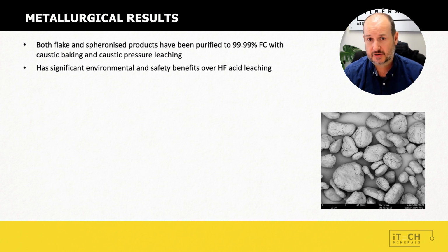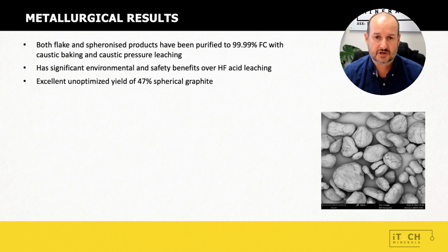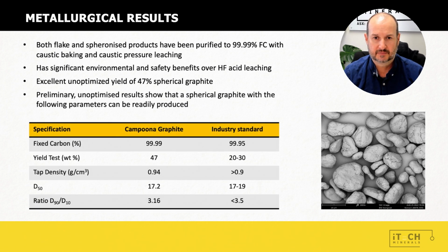Both the flake and the spheronized products have been purified to 99.99% fixed carbon using both caustic baking and caustic pressure leaching. We were also able to achieve excellent unoptimized yields of 47% spherical graphite. So from that purified flake product, 47% of that material was able to be converted into a spherical graphite product.